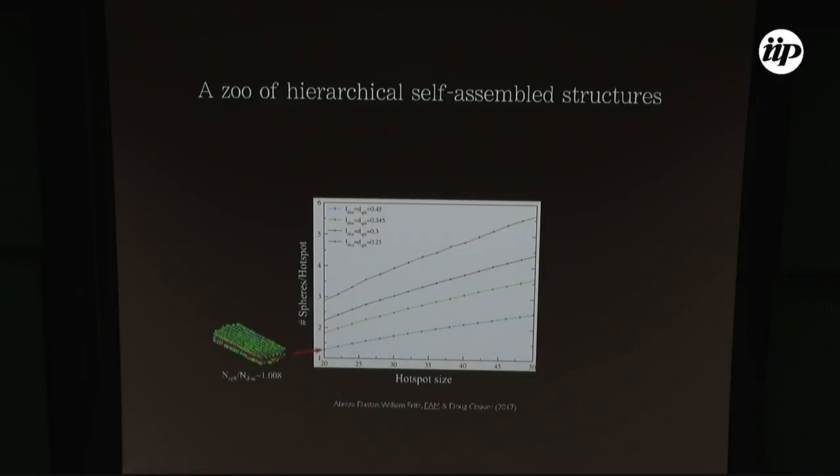So, okay, when we have very fat ellipsoids, and they don't have a lot of area that wants to contact solvent, they're pretty much flat. If we shrink them a little bit, what we find is that they get these nice helicoidal structures. Shrink them even more, we can get orthogonally arranged, again, flat bilayers, but if you grow them, they will become sort of potato chip shape.